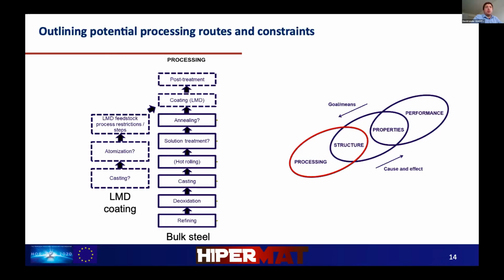And all of this could lead to different bottlenecks in the development, and is really related to the LMD coating with the optimization or the processing of the LMD coating that is putting a lot of constraints on the use of the refractory high-entropy alloys in this project, since there are a lot of unknowns. So the focus currently is more towards the steels, the superalloys, and the transition metal high-entropy alloys, with some aluminum additions for potentially added strength from precipitates.